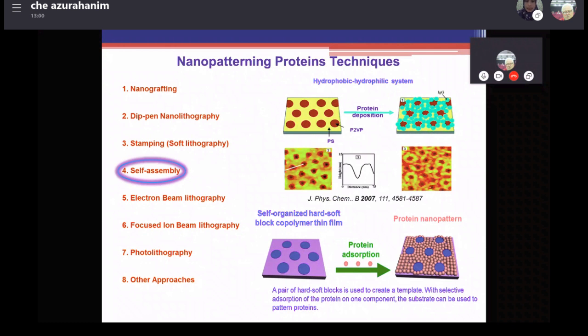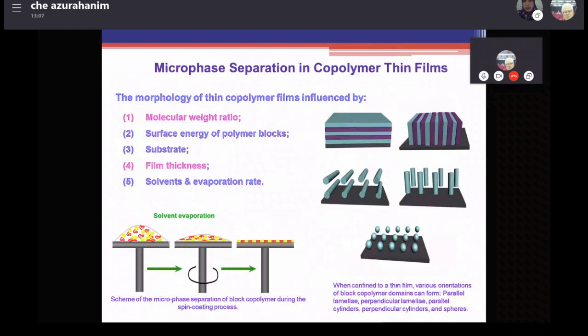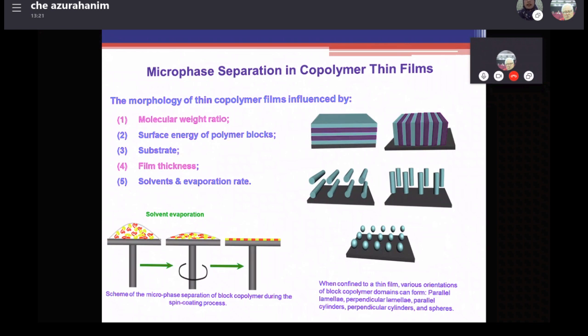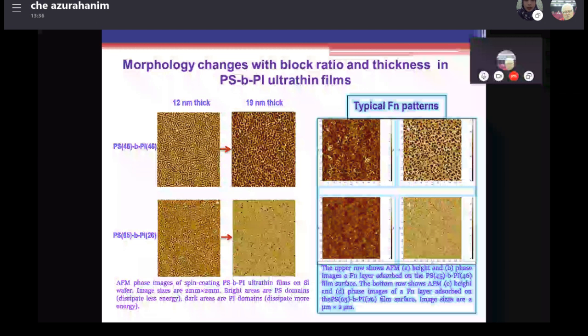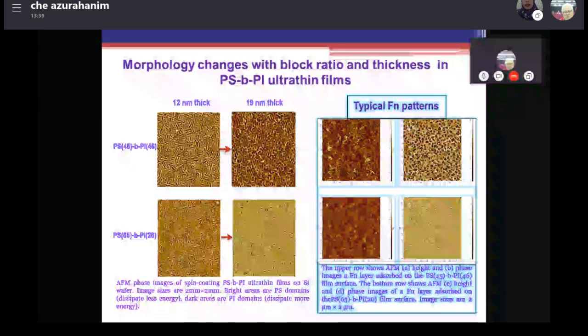In terms of the microphase separation in polymer thin film, the morphology of the thin film can be influenced by several factors, such as molecular weight ratio, surface energy of polymer blocks, substrate, film thickness, solvent, and evaporation rate. What we observe is the morphology changes with block ratio and thickness in the PS-b-PI. PS is polystyrene and PI is polyisoprene. We can see here the AFM images of our thin film before and after protein adsorption. Okay, here is after fibronectin has been coated on our block copolymer.